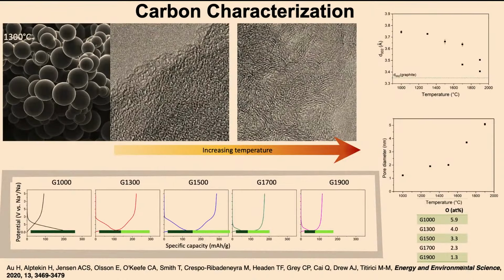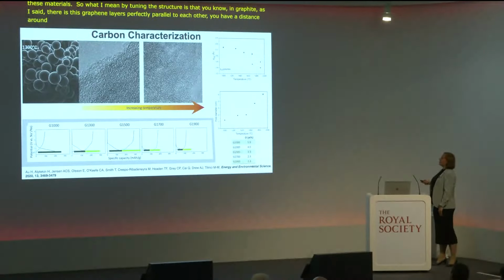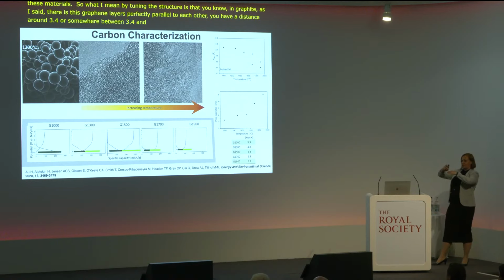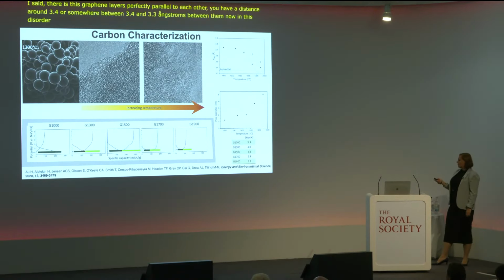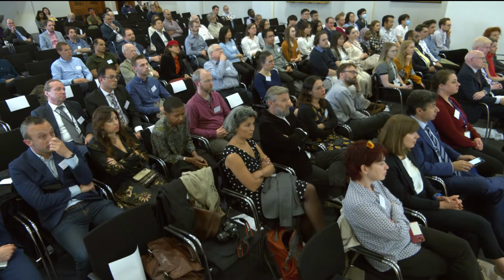What I mean by tuning the structure is that, in graphite, as I said, there are these graphene layers perfectly parallel to each other, and you have a distance of somewhere between 3.4 and 3.3 angstroms between them. Now, in these disordered carbons, you have different spacing between these graphene layers, and we can tune this spacing by tuning the temperature at which you prepare these carbons. We can also tune the pore diameters in between these graphene layers, and we can play around with defects. So imagine this house of cards, or one card that could have some oxygen functionalities or other imperfection. This seems to be quite important for storing sodium.